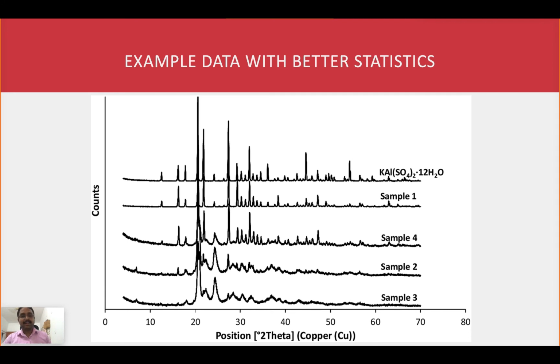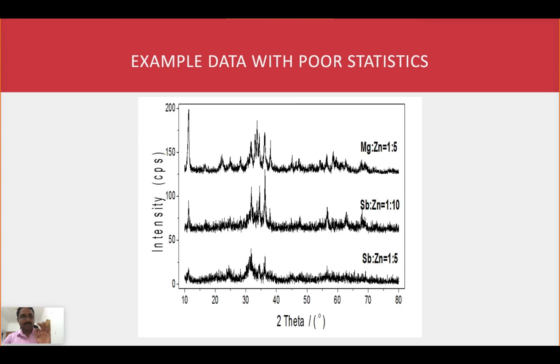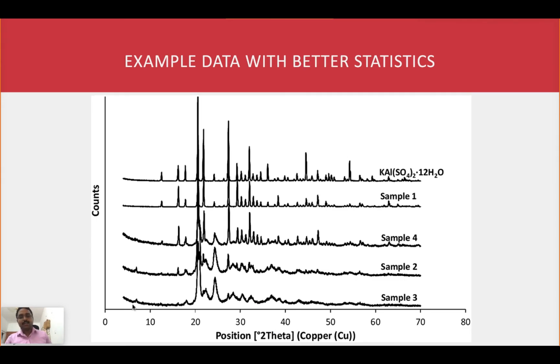This is a better, I will not say good, a better. Why better? You can see different peaks are shown correctly, or you can distinguish between peaks and background. So what is background? I'll go back to the slide here. You can see these small things which are coming out. If you don't keep your sample also, you will get this small line. It is called background radiation. So the background will always be present whether your sample is there or not. You can take empty holders, then also you will get this small background. That is what I am telling you here. The background is less and your peaks are distinguishable. Then it is data with better statistics.